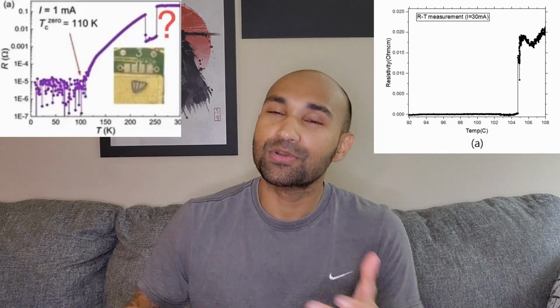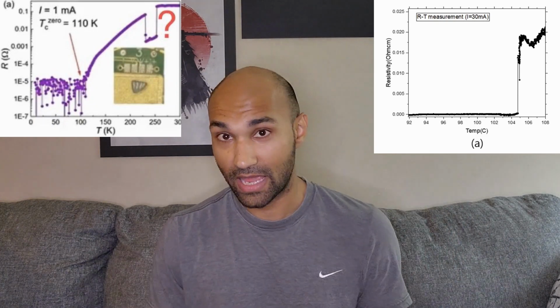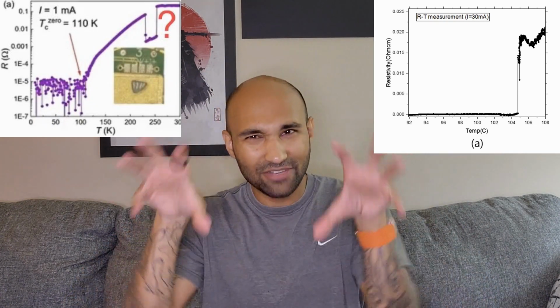Another thing that I wanted to point out is that the temperature resistance curve is quite different from the original paper. So because of this difference, you almost got to wonder, maybe were some of the impurities important? Maybe it was too pure, or just the sample, like the heterogeneous crystals, maybe the structure of one crystal versus the other, even with the same X-ray diffraction profile, has totally different properties. So we don't know that very well. So they measured the resistance. They also tried to measure Meissner effect and the diamagnetism.